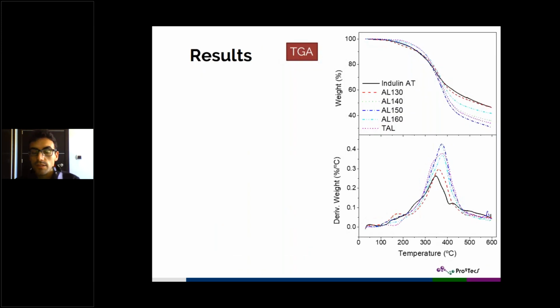Well, let's continue with the thermodynamic analysis. As we can see here, the Indulin AT lignin is the one that shows the highest residue, or let's say the highest resistance to temperature. And then as we increase the acetylation temperature, we increase the weight loss at the main event. So finally getting a lower residue.